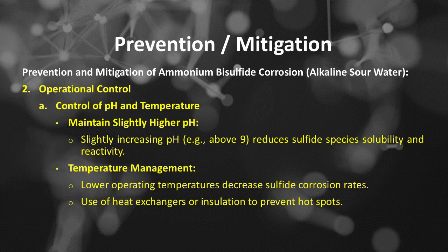Prevention and mitigation of ammonium bisulfide corrosion in alkaline sour water. Number 2 is operational control. Number A, control of pH and temperature. Maintain a slightly higher pH; slightly increasing pH, such as above 9, reduces sulfide species solubility and reactivity. Control and manage the temperature, as lower operating temperatures decrease sulfide corrosion rates. Use heat exchangers or insulation to prevent hot spots.